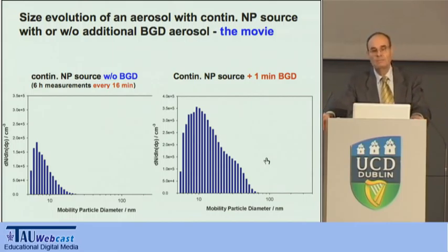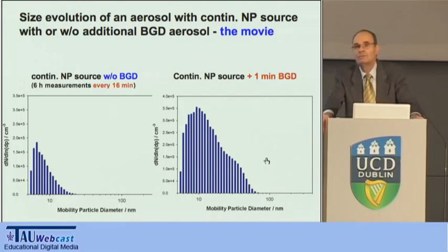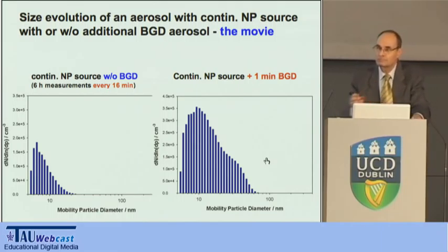Now, if you emit 10 nanometer particles and they attach to, let's say, 200 or 300 nanometer particles, they're gone from the size spectrum. You won't see them anymore. But chemically, they're still there. So if you could do speciation, and of course with platinum it's not terribly hard to do, platinum is, for example, also catalytically active, and you can then check whether you have your same catalytic activity. Well, yes, they're there, except they're no longer in the size spectrum where you've been looking at them.